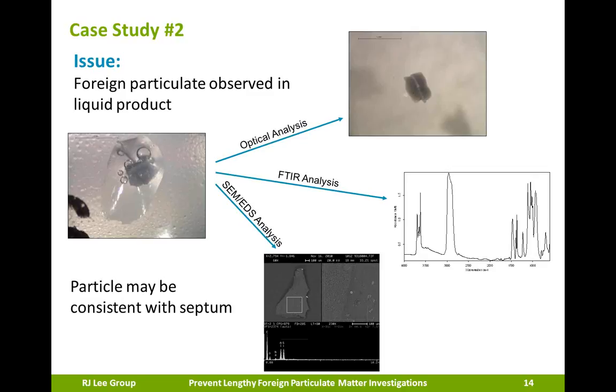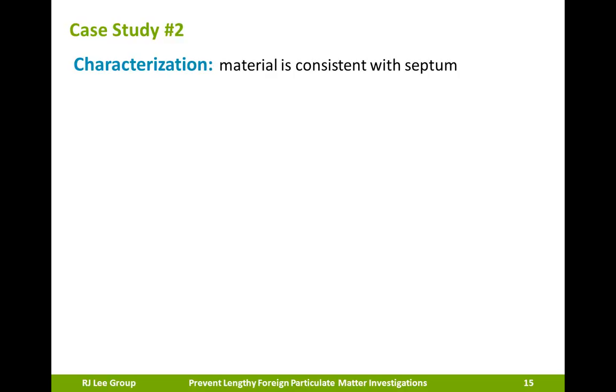This is consistent with a butyl rubber-based material, and it contained indications of silicates being present. The SEM-EDS analysis revealed a carbon-rich matrix with elements of aluminum, silicon, oxygen, and sodium. When it was further investigated, it was determined that there were small inclusions that were rich in silicon and aluminum, indicating there was an aluminum silicate filler material, and this is something that we commonly see in rubbers. So the characterization revealed the butyl rubber with aluminum silicate as possibly consistent with the septum material. However, we wanted to be able to confirm this.